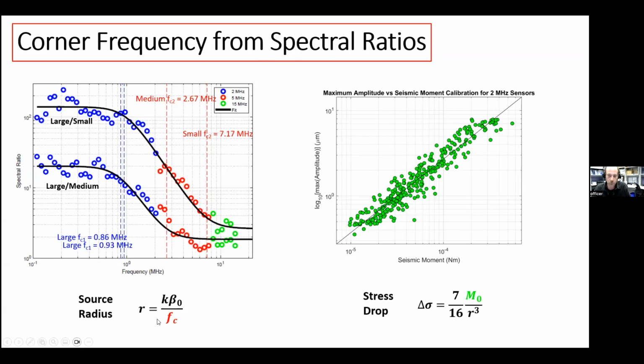So once we have the corner frequencies, we can estimate the source radius. If we want to get the stress drop, we also need to know the magnitudes. This is actually pretty difficult because you have an acoustic little earthquake that happens here, and then it has to travel through a medium, and then you measure it at your sensor. So the actual size of the event that created that, it's kind of difficult to know.